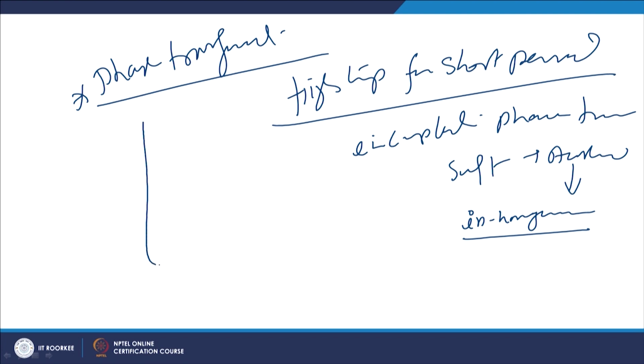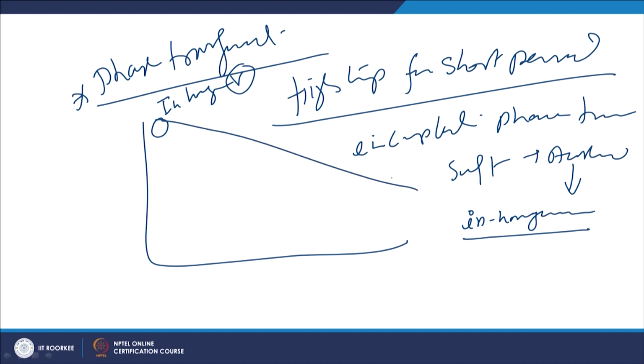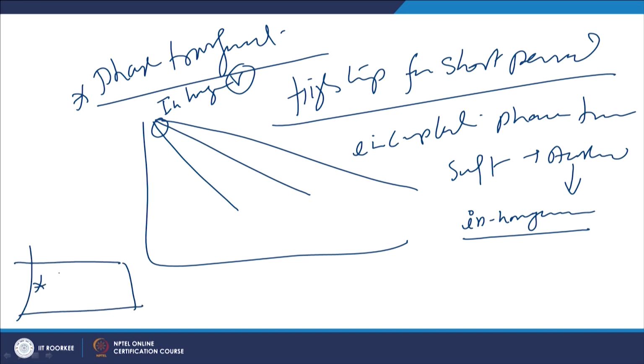rate. So, if we see here, here we have the inhomogeneous austenite available for transformation, and it will be subjected to the different cooling rates as per the distance away from the fusion boundary. If the point is close to the fusion boundary, it will be experiencing higher cooling rate, and on increasing the distance away from the fusion boundary, the cooling rate will keep on decreasing because of the varying thermal cycles which are experienced by the weld metal.